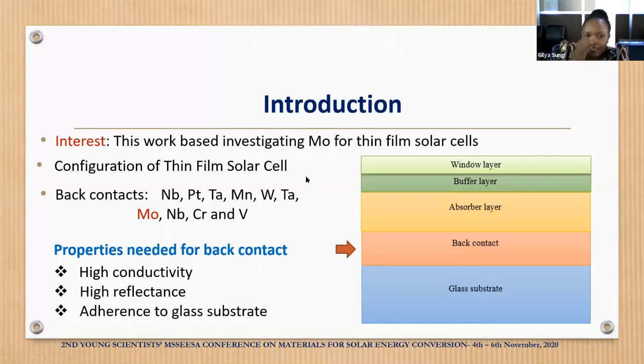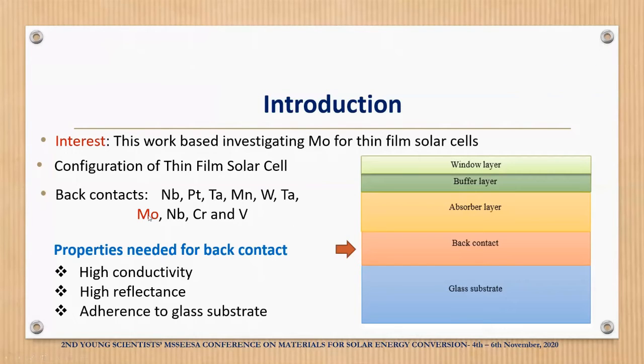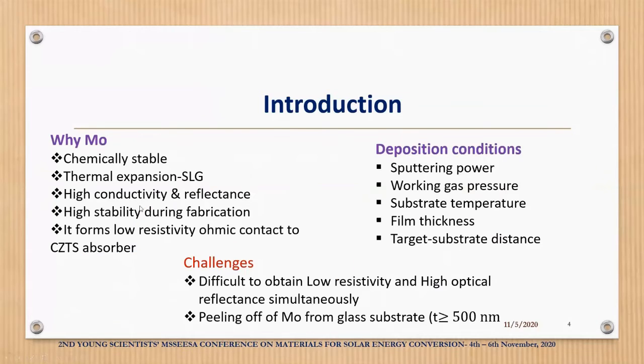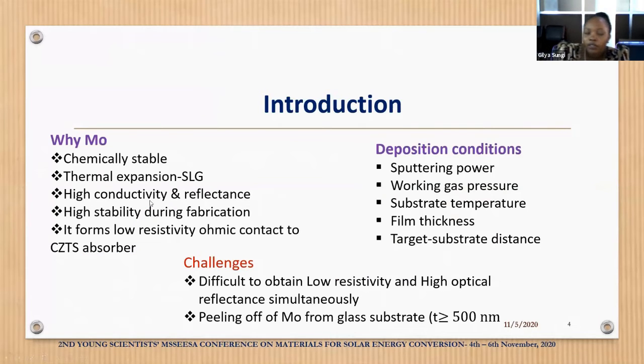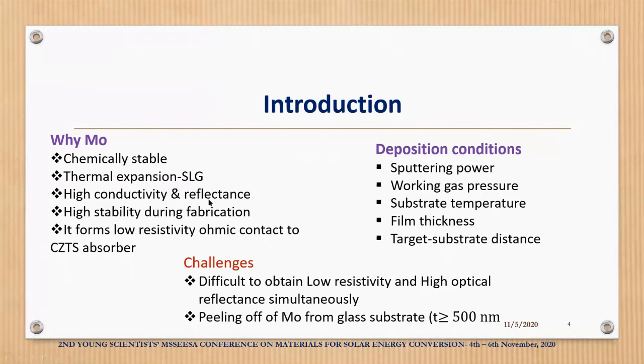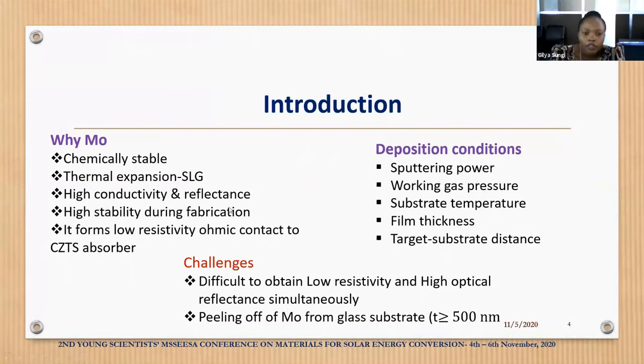The investigation showed molybdenum has the best properties compared to other materials. Then it has been selected to be used as back contact. This is because molybdenum is chemically stable, and there is matching of thermal expansion of molybdenum and soda lime glass substrate. There is high conductivity and high reflectance, which does not degrade at high temperature. Also, it has high stability during fabrication, and it forms a low resistive ohmic contact with the absorber.